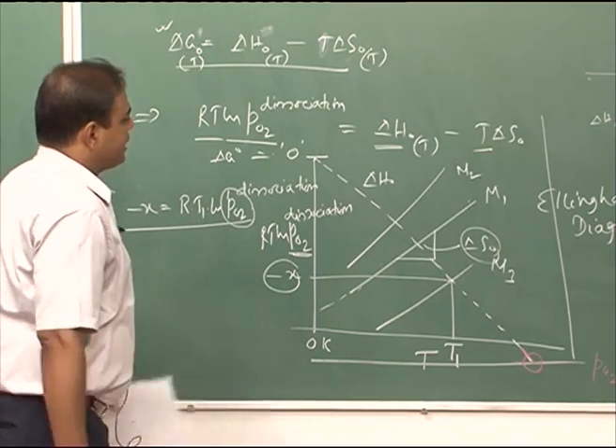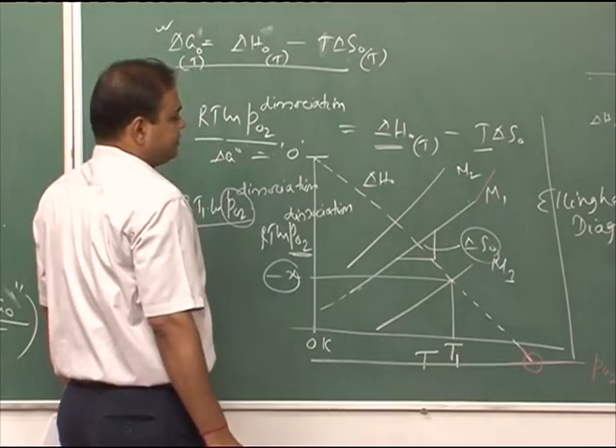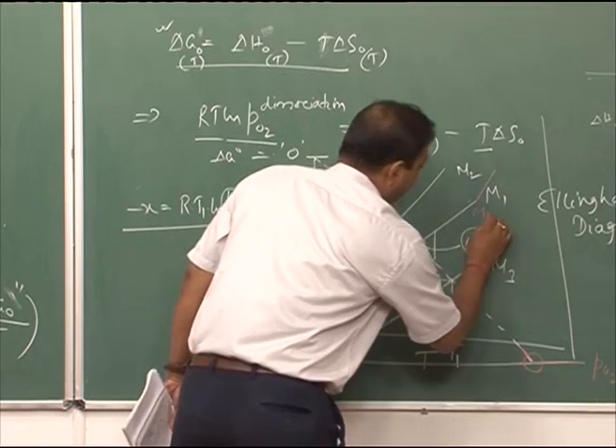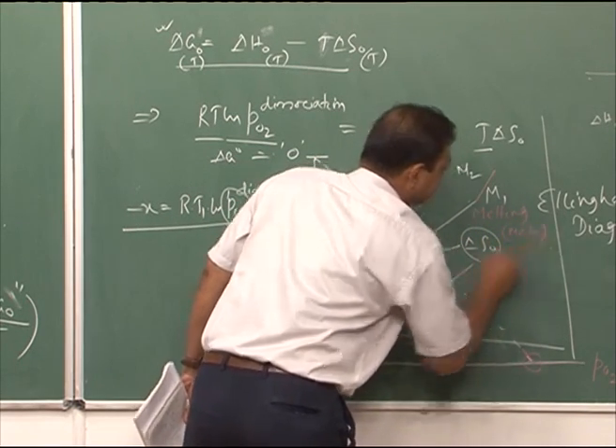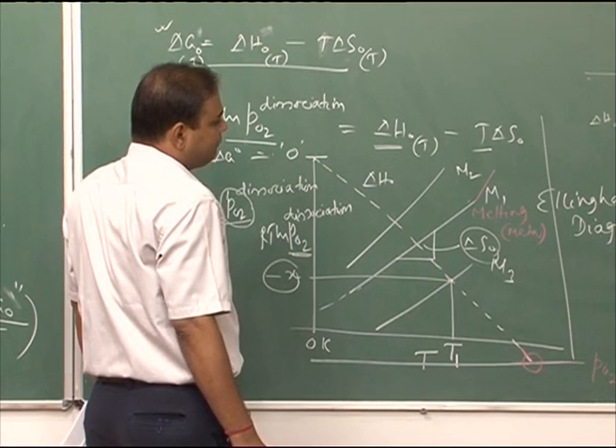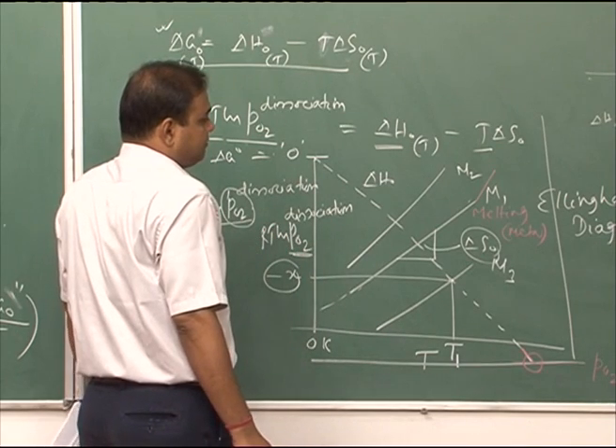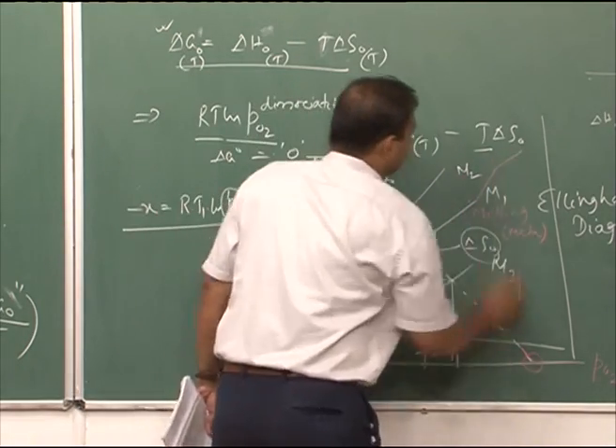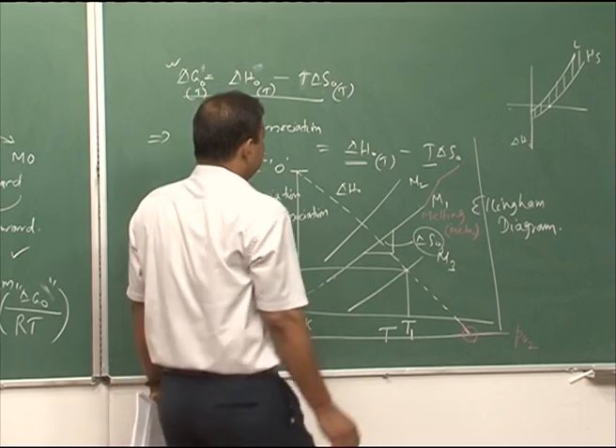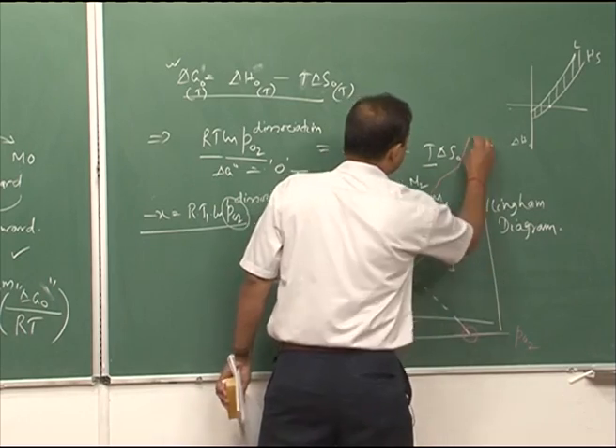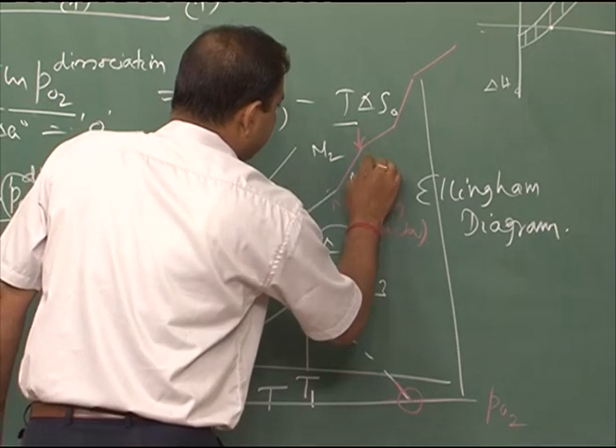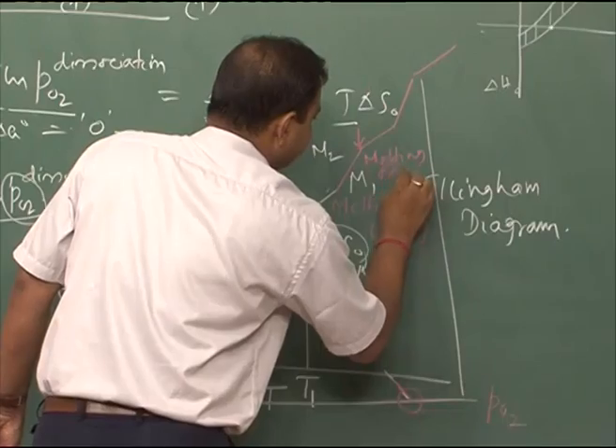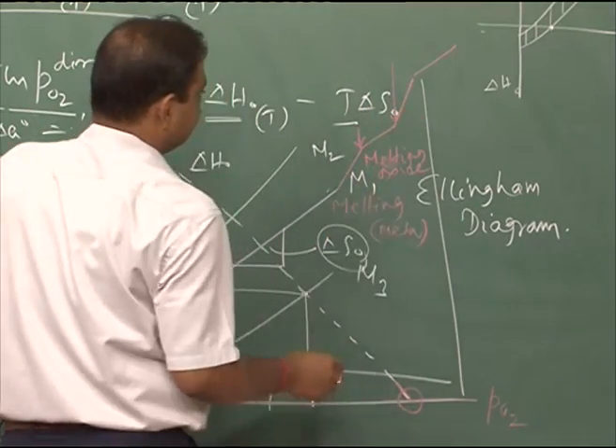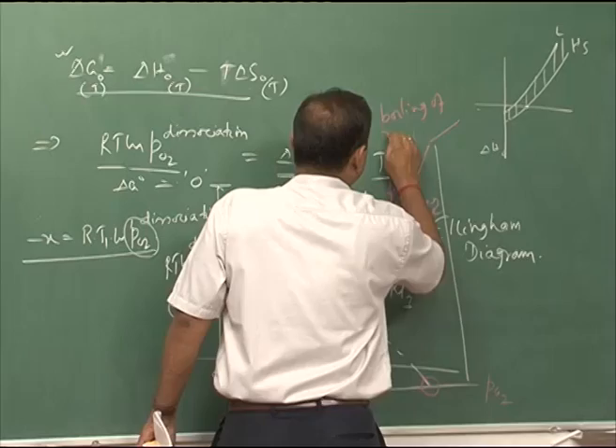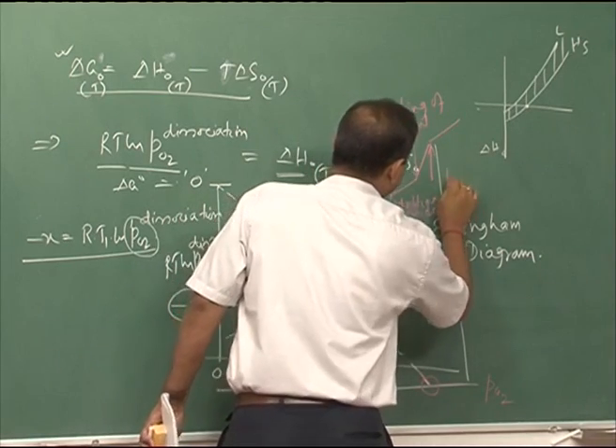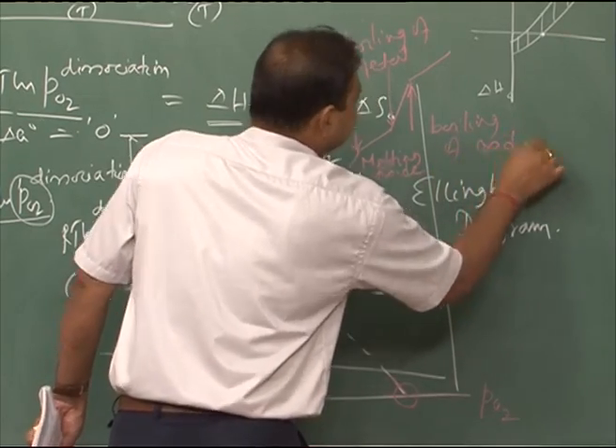Now, in the Ellingham diagram, you might find that there is a slope change whenever there is melting of the metal taking place. If there is melting of the oxide, then you will find that the slope is again decreasing, and if there is boiling of the metal, the slope again would increase, and if there is boiling of the oxide, the slope again would decrease. So, this is melting of the oxide, this is boiling of the metal, and this is again boiling of the oxide. Like that the slope would change.